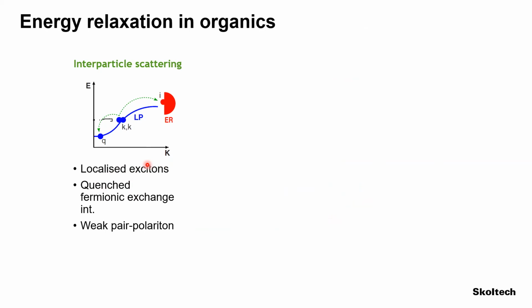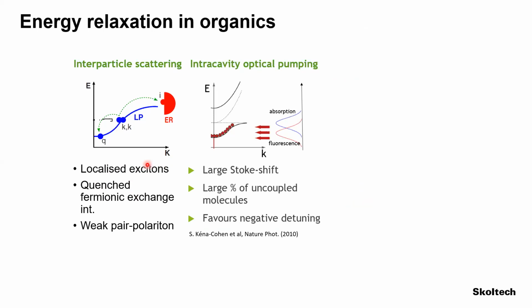Now there is another way, that of intracavity pumping. Not all molecules inside the cavity of the semiconductor that you embed between the two mirrors are strongly coupled. Some are at the antinode of the field, at the maximum of the field, but some molecules lie on the nodes of the field. And therefore, you have material which is not strongly coupled and fluoresces resonantly, due to the Stokes shift, within the lower polariton mode. So due to the large Stokes shift, you can really now within the cavity pump the lower polariton dispersion and increase the density of polaritons at the ground polariton state.